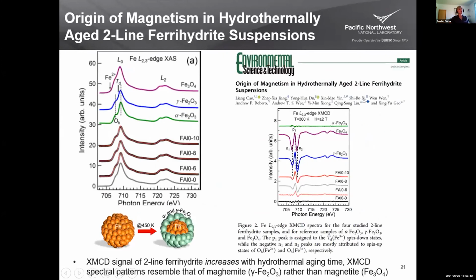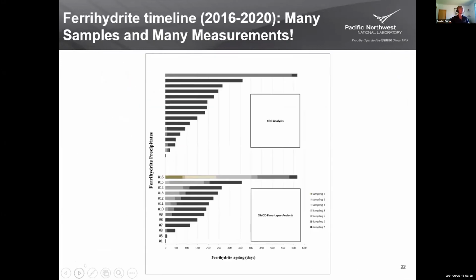There's also been studies looking at hydrothermal aging over time, and demonstrating again that the magnetic structure of ferrihydrite looks very similar to maghemite, which you would expect, because that is the fully oxidized form of magnetite with no iron 2 remaining in the structure. But we wanted to take it a step further and look at 2-line ferrihydrite over a very long period of time, and what affects the magnetic properties and the structural changes over those long time periods.